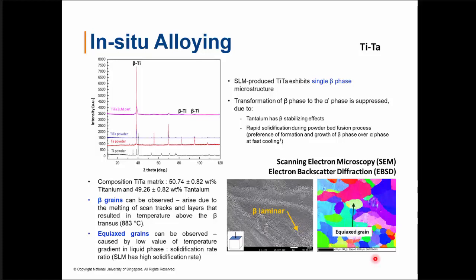We studied the alloy fabricated by powder bed fusion in detail and found that it achieved what we set out to achieve — creating beta titanium alloys. Characterization techniques were used to validate the alloys formed by the in-situ alloying approach, confirming the desired results. The beta phase was predominantly found in the alloy, showing that tantalum has a beta-stabilizing effect that suppresses the formation of the alpha-prime phase typically observed in other titanium alloys after powder bed fusion processing.